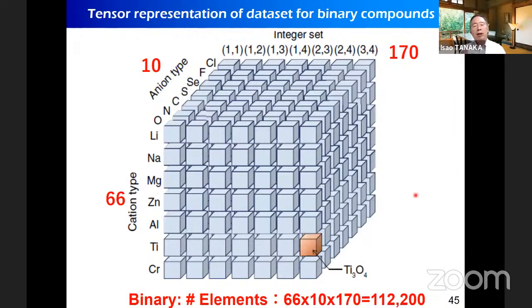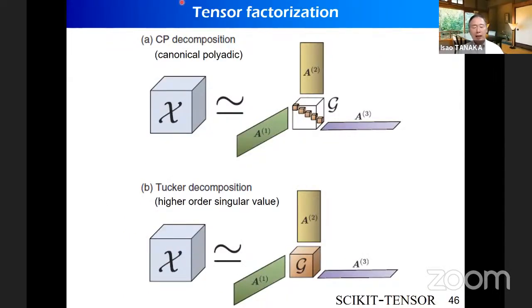So instead of using the rating matrix, we have chosen tensor representation of the chemical composition. Here is a cation type 66, anion type 10, and the integer set. By the way, this is for the binary, so it is composed of 100, 1,000. But this is already a third-order tensor, and if we want to draw ternary system, it becomes a fourth-order tensor. So it is not easy to show in an easy way. But anyway, we have chosen the tensor factorization technique, and there are many tensor factorization techniques available, for example, in the scikit-tensor open software. And we have chosen that Tucker decomposition technique.